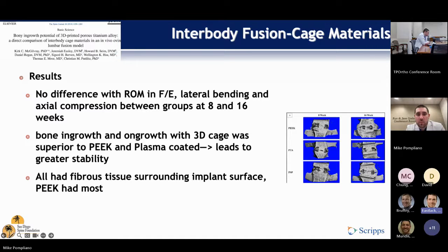And likewise, with PEEK, if you change its chemistry, if you put HA in it, you can basically mimic the way titanium serves. You can allow it to be more bioactive, and then its topography also can make a difference. So there's porous PEEK, there's trabecular PEEK. There's all these different modifications that have bioactive influences, and then the complexity of the structural stiffness itself.